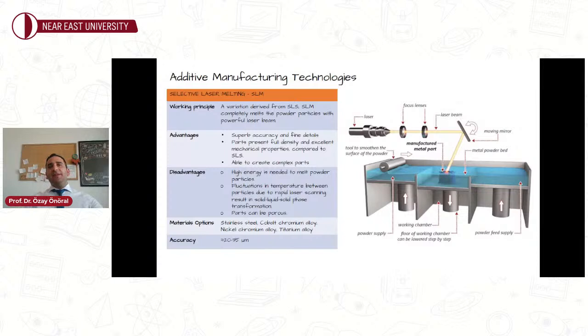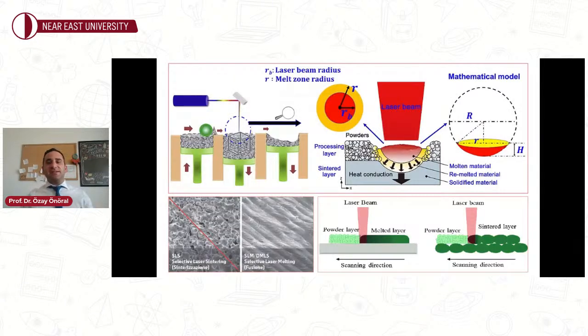SLM is another technique that can be thought of as a variation derived from the SLS technology, because the same steps are applied in both techniques. I said to you that the main difference is that SLM completely melts the metallic powder particles with a powerful laser beam, and a melt pool is formed. Thus, at the end of the production phase, metallic parts with almost 100% density and superior mechanical properties are obtained without the need of any extra processing or post-processing. Moreover, it is advantageous to carry out the process under inert gas, since liquid metals cannot wet the surface because of the surface oxide films.